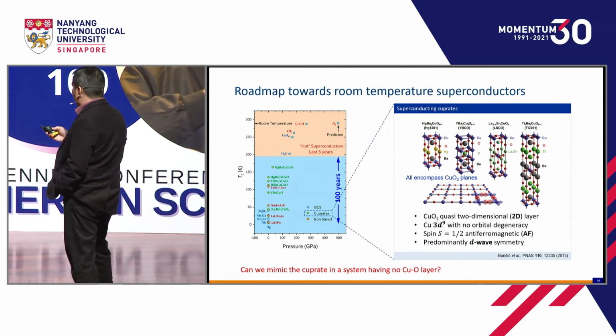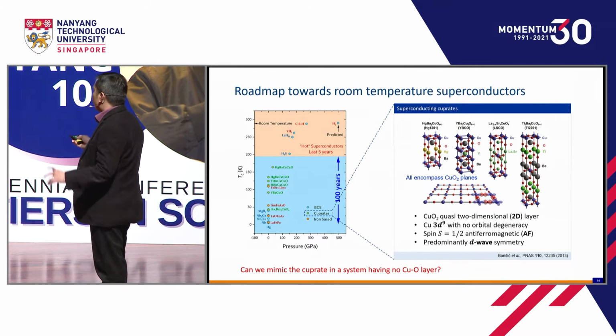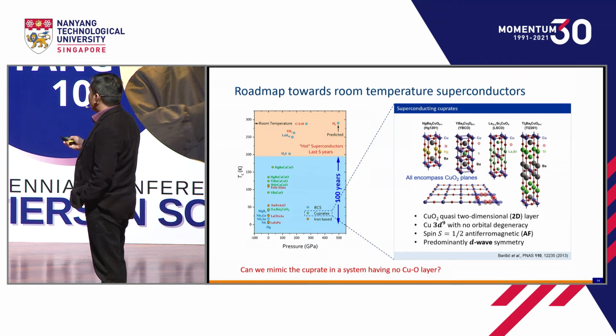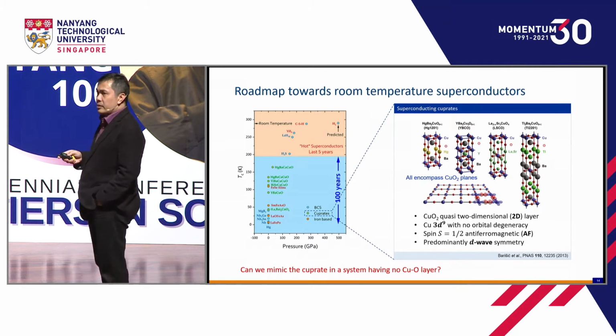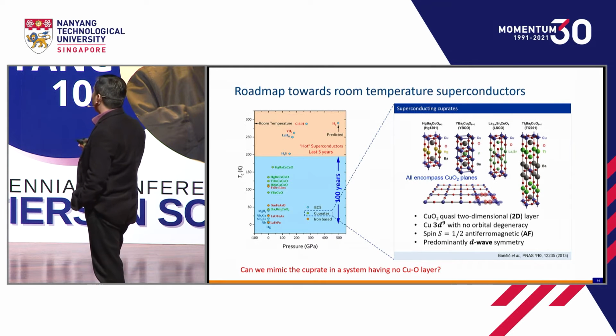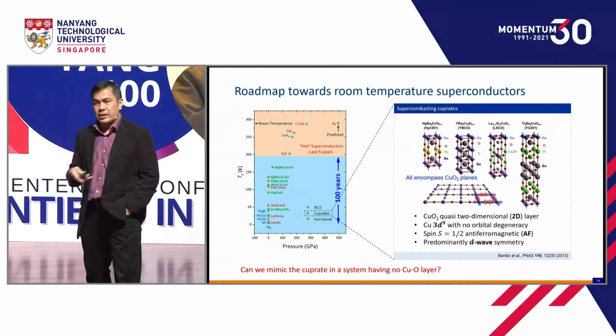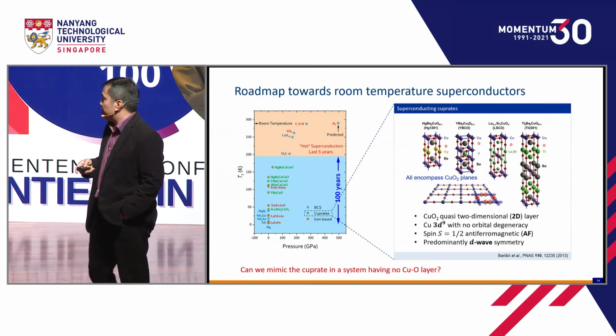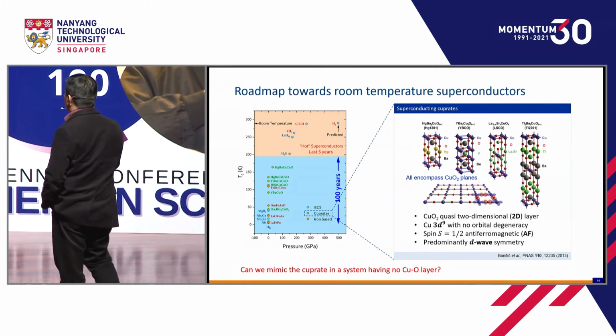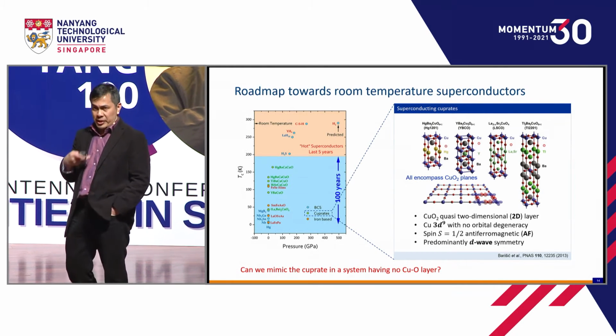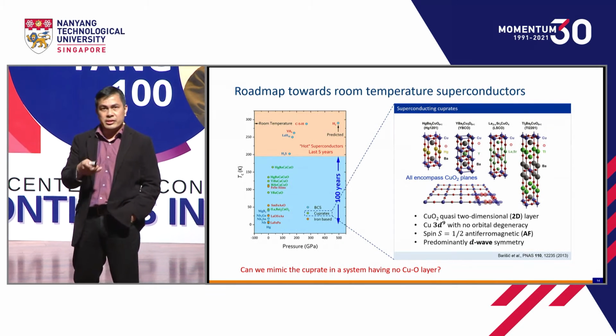So if we look at the cuprate, there are many critical features. One, as I said before, is this copper oxide plane. And then one critical aspect is the electronic state, which has 9 electrons in the d orbital of the copper atoms, okay? That is what I would like to point out. The other one is the spin half, which becomes antiferromagnetic in the parent compound of the cuprate, okay? And then the symmetry, having predominantly d-wave instead of s-wave, as in the BCS theory.